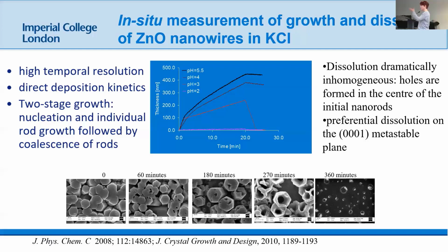So it deposits as these individual rods, and the reason it's doing that is because this top surface here, the 0002 surface in zinc oxide, is extremely polar, right? So if you think about the zinc oxide structure, it goes zinc ions, oxygen ions. So any slice across that crystal structure has a really high surface energy because it's all charged. So it doesn't like that surface, so it tries to minimize it, right? That's why we get a small top surface and long wires. It's minimizing that polar surface.